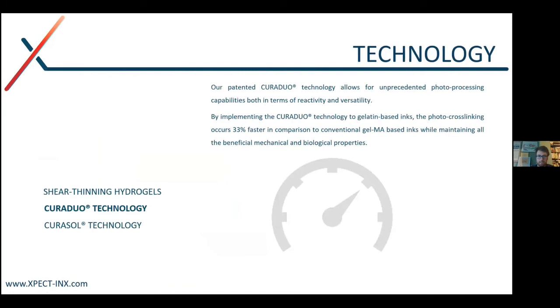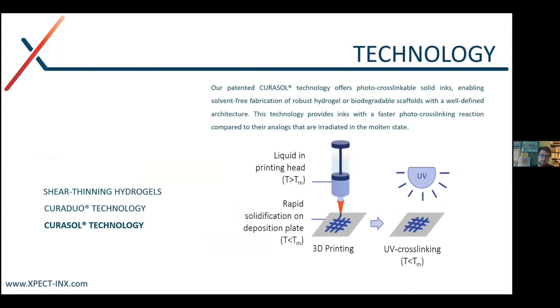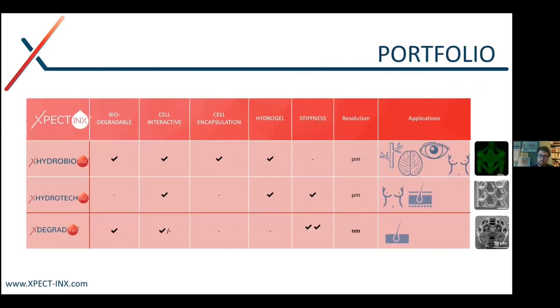So we have a patented CURADUO® technology, which results in faster cross-linking for biomaterials. For example, if we apply this technology on gelatin-based materials, we can process it 33% faster in comparison to conventional GelMA-based materials. And then the second technology is, again, the solid-state cross-linkability for the reasons I just mentioned. So this brings us to our portfolio there, where we have our hydrogel ink, HydroBio, which is gelatin-based. It's biodegradable, cell interactive, allows for cell encapsulation. It's a hydrogel that can be processed down to 1 micrometer resolution.